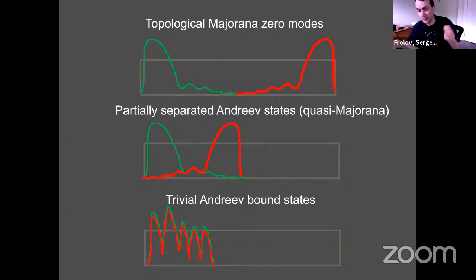Okay, so we found this evidence of Majorana, this sticky, resilient zero bias peak. But a few years after we did that, came an interesting surprise. Nature had a surprise for us. There was another possibility to explain the same data. We mapped it out pretty well, and we were still left room for doubt, but to be honest with you, we were pretty sure that it was Majorana. But then an interesting realization set in, and this is basically my way to summarize it. What you want is this top picture, an electron split in two parts, green and red, that are not overlapping. Those are the topological Majorana modes, separated and protected.